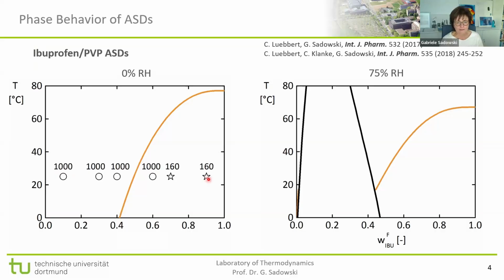And from time to time, we made a PXRD of the samples, and what we saw is that the samples right of the solubility line did indeed crystallize, and the numbers you see here, these are days. That means these two samples crystallized after 160 days, whereas the other ones remain amorphous. This is clear for those because they are left of the solubility line. They will stay amorphous forever. So this is a safe region.